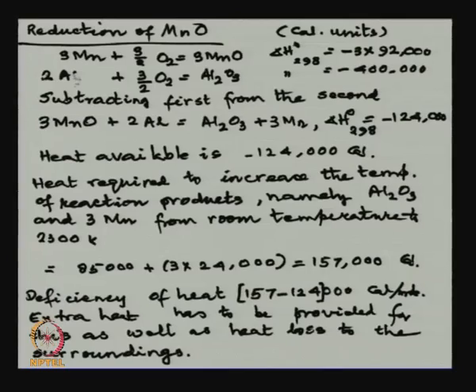Reduction of MnO. We can write 3 Mn plus 3/2 O2 gives 3 MnO. Enthalpy change is this, because in terms of MnO it was only 92 multiplied by 3. For aluminum oxide formation, it is this. So, if we subtract this from that, we get for this reaction, 3 MnO plus 2 Al gives Al2O3 plus 3 Mn, the delta H naught value to be like this. So, this is the amount of heat available with us if this is the reaction that takes place.